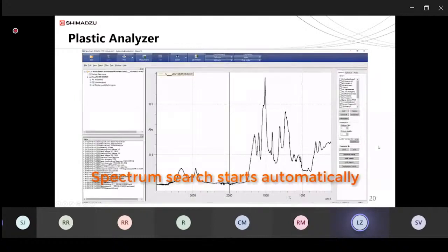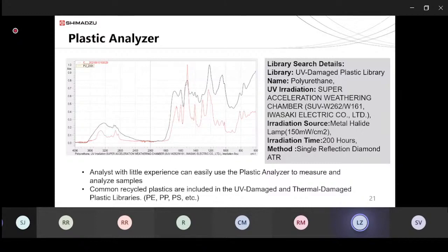And then we can look at what's available in the data report. So in this example, the top hit for the sample is a polyurethane sample that's been UV irradiated for 200 hours. The red curve is our sample measurement, and the black curve is the search results polyurethane spectrum. And in this report, we will have more detailed information about the polyurethane sample.